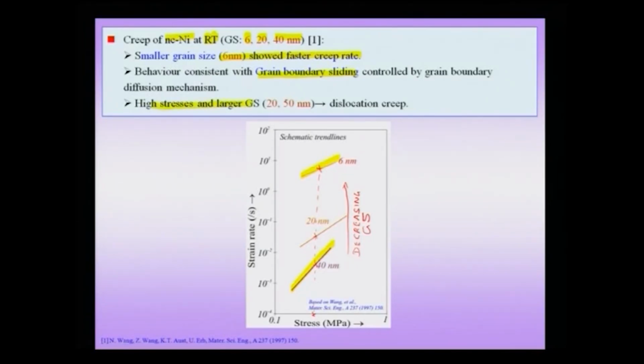But at high stresses and larger grain sizes, that means if I go to the higher stress regime, and if I am talking about the larger grain sizes like the 20 nanometer or 40 nanometer samples, then dislocation creep seems to be the important mechanism. So, we can replace this 50 by 40, because this was the one originally involved in the study. So, this is a very nice example, the creep of nanocrystalline nickel at room temperature, wherein some of the initial expectations are actually fulfilled, and within this small grain size regime of about 6 to 40 nanometer, we are actually seeing a switch in the mechanism. The small grain size seems to undergo grain boundary sliding accommodated by diffusion, while the larger grain sizes under higher stresses seem to undergo dislocation creep.